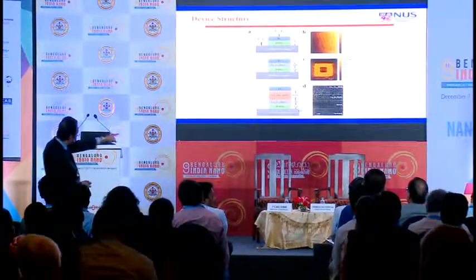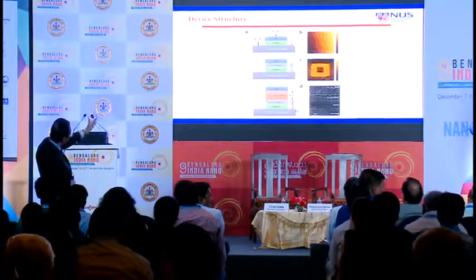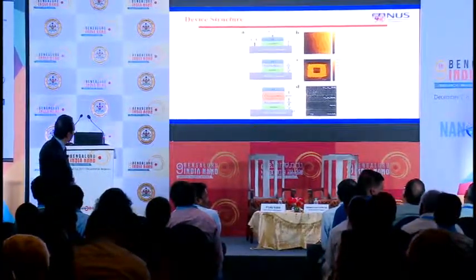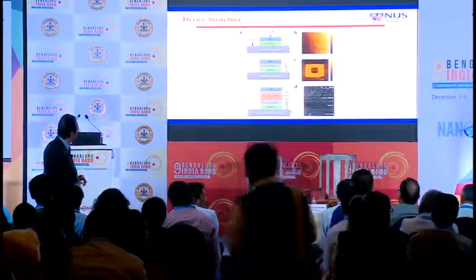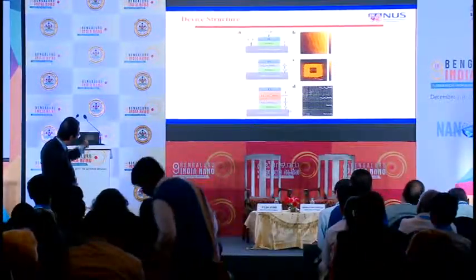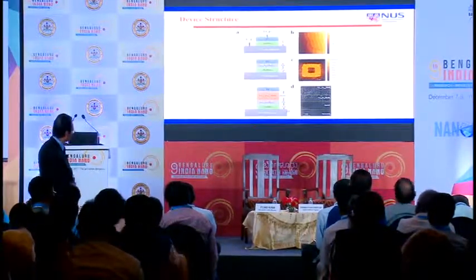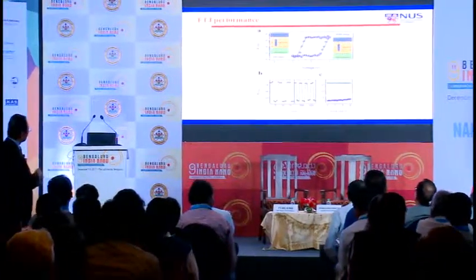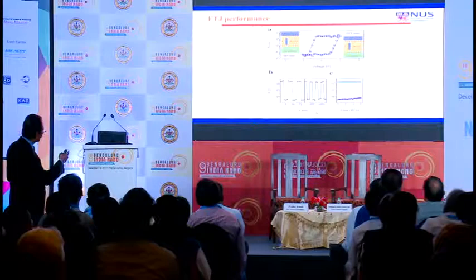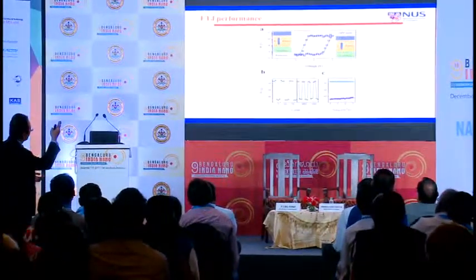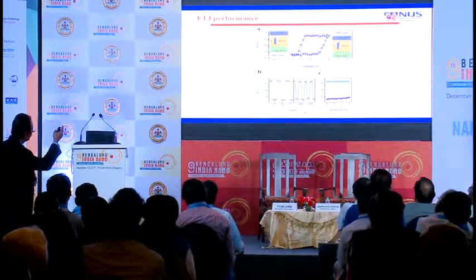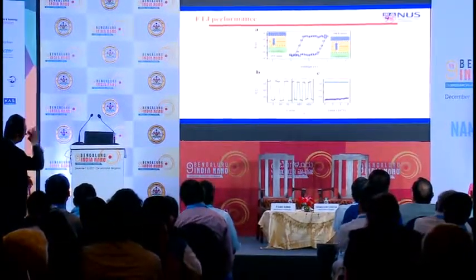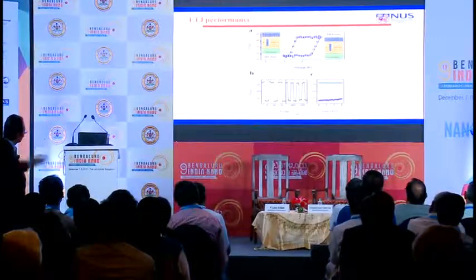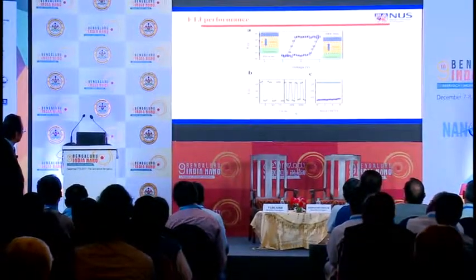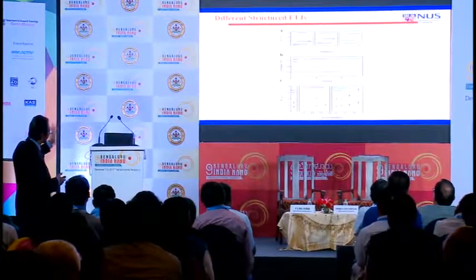Now you can see here in the bottom right-hand corner, what we did is make the device more complex by adding more and more interfaces. The bottom right-hand corner shows the TEM cross-section, showing beautifully atomically ordered growth of all these layer structures. And now what we see is the following. This is a typical resistance versus voltage curve. As I increase the voltage, at 1 volt the device turns on, it reaches a maximum voltage of about 2 volts, and then when I turn the voltage back, it maintains its hysteresis, and then it switches off on the negative side. And so these are the two memory states that you're going to be using.